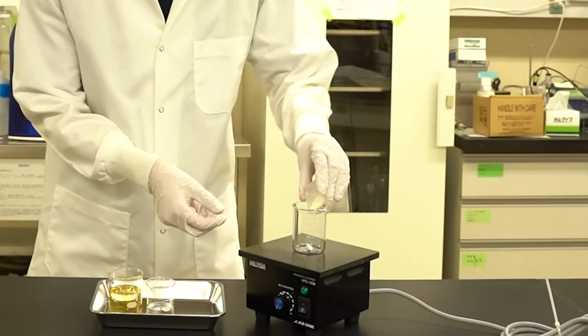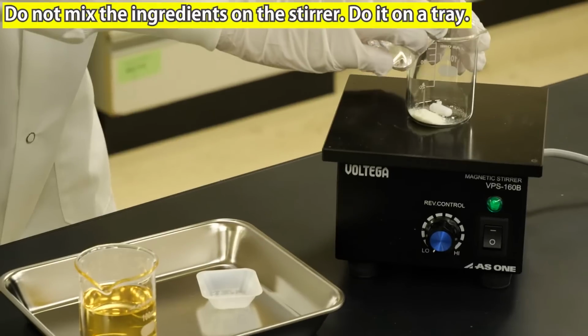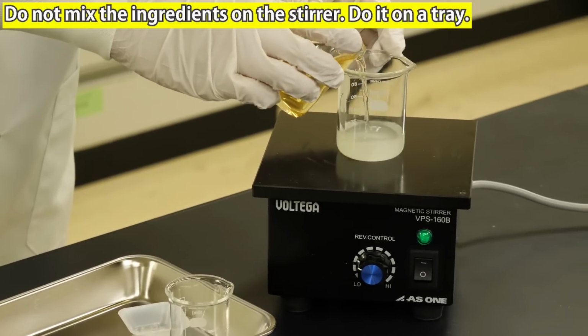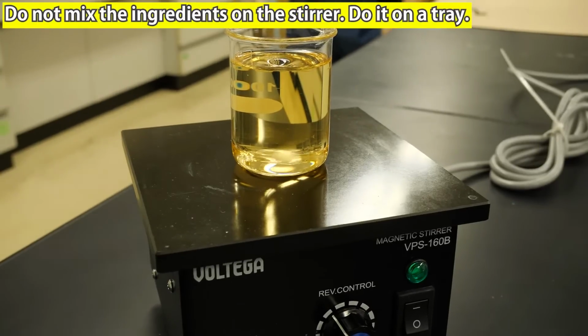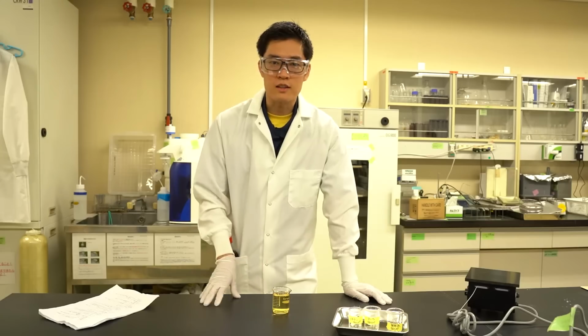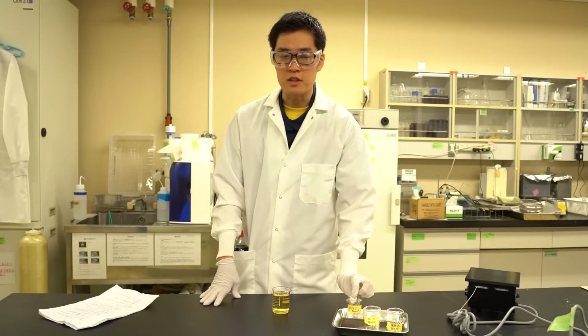I'll put the powder in first. I'll pour one of the liquids. Then I'll pour the other liquid. It's done. Keep stirring using the stirrer until the powder dissolves. Now the electrolyte is complete. I'm going to let the capacitor elements be impregnated with the electrolyte.